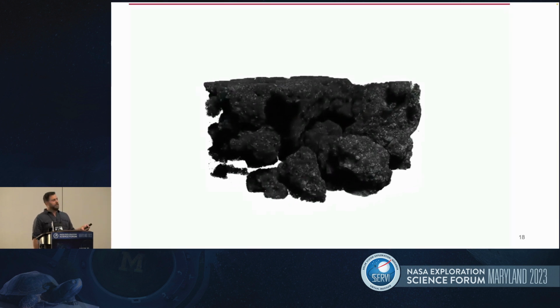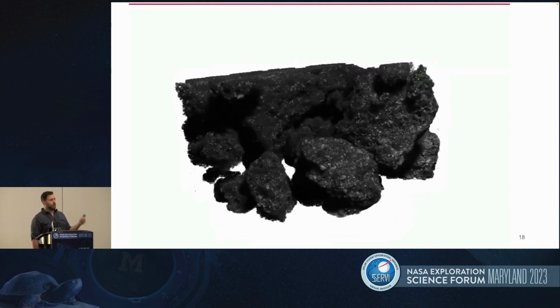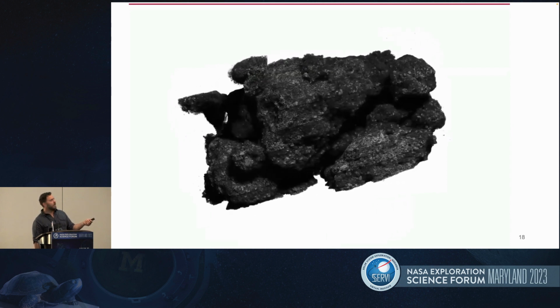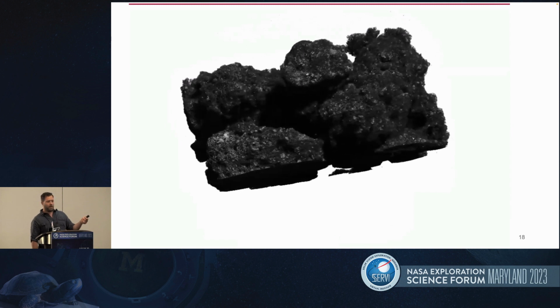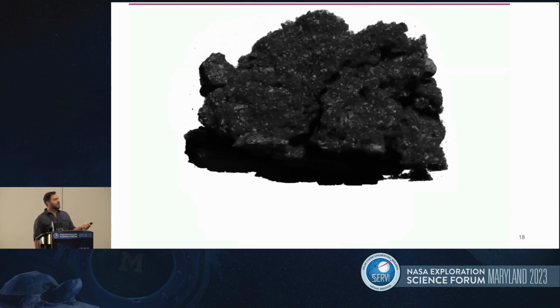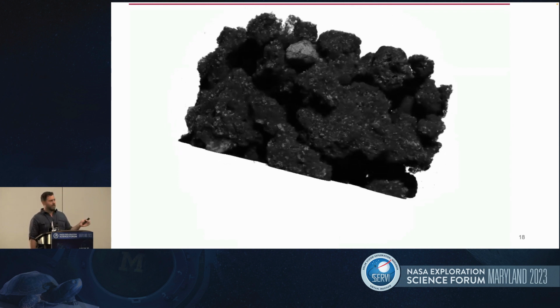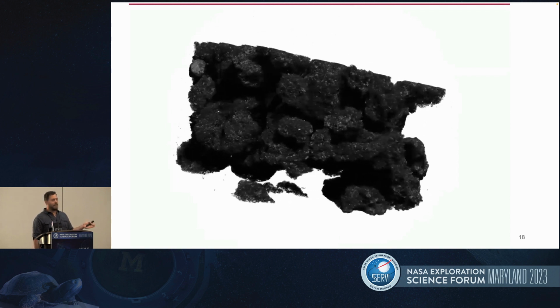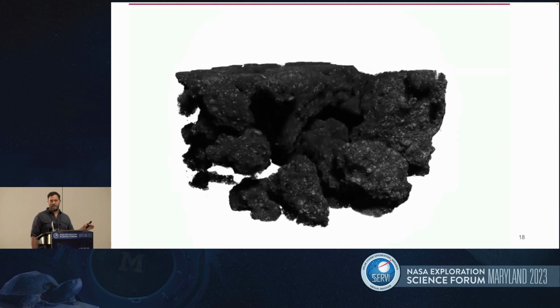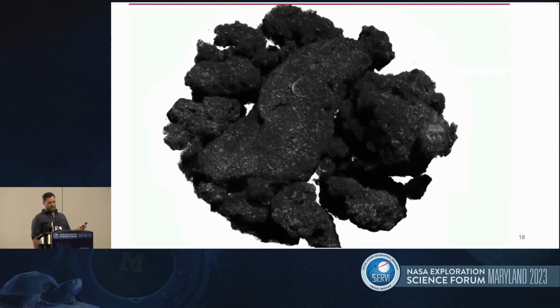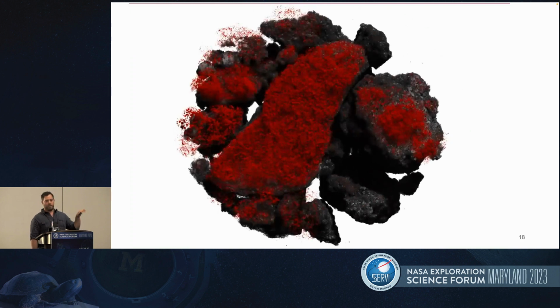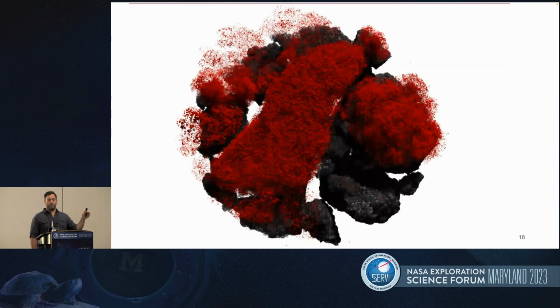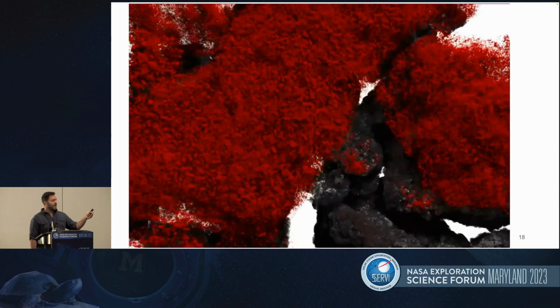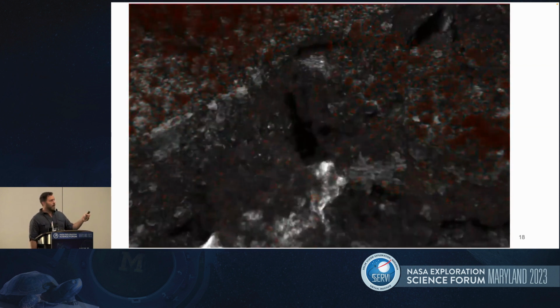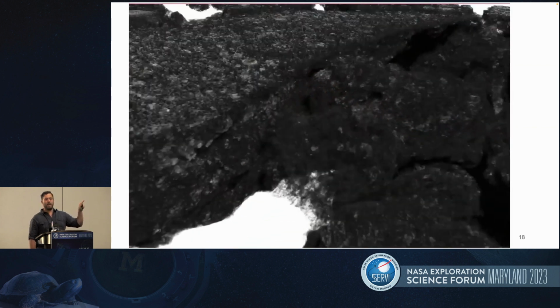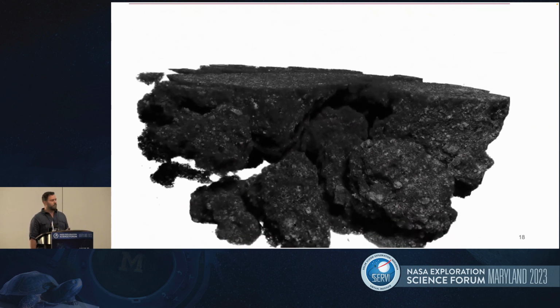Microtomography allows you to make non-destructive 3D maps of the structure of your sample. Here is this regolith material that we're using. As you can see, you can resolve the brighter features, which are crystallites in a glassy matrix. The grayscale values here are actually quantitative, meaningful X-ray attenuation values that can potentially be mapped to the specific phases of the crystallites, although we haven't even got there. Because it's a non-destructive technique, it lets you go inside your grains and also study the porosity that exists within the grains, which can be another place where trapped volatiles could be sitting. And you can understand the topology of that pore network, the transport properties, and the structure of the grain contacts, which is essential for this sort of study.